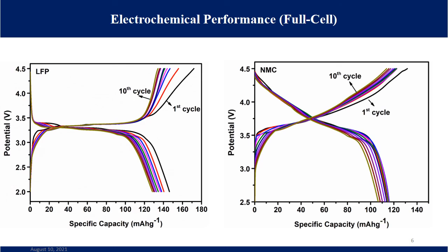we used LFP and NMC cathodes. From the GCD profiles, it is observed that the cell with LFP cathode has delivered an initial capacity of 146 milliamp hour per gram and retained a capacity around 127 after 10 cycles. For the NMC cathode, the initial discharge capacity of the cell was 116 milliamp hour per gram and it has retained a capacity around 106 milliamp hour per gram after 10 cycles. The capacity loss can be ascribed to the formation of the SEI layer.